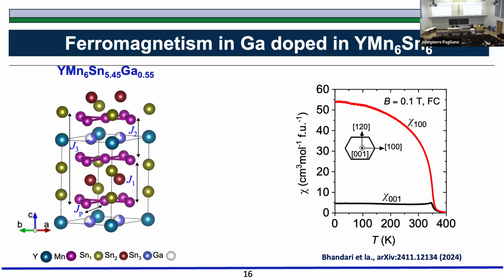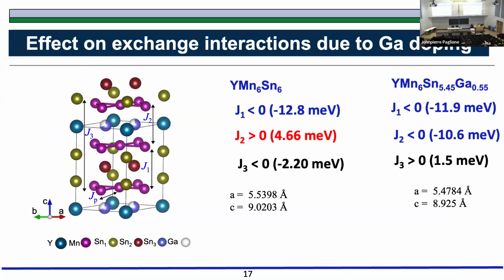And why does it get into the ferromagnetic state? It is again because of the way that the gallium changes the interaction between these elements. And what we did is we took the help of some calculations for this. See here in the parent compound, this was negative, this was positive, the value was about 5 here. Now this becomes significantly larger than negative in this case.